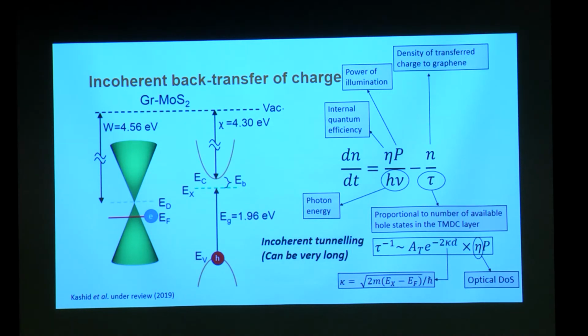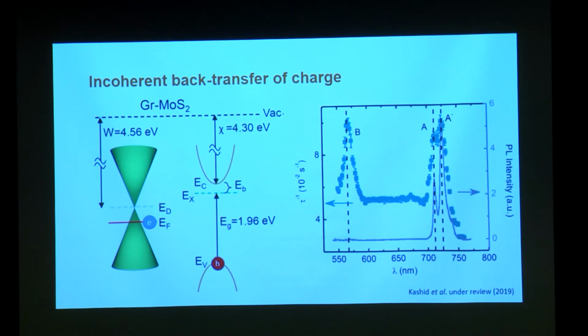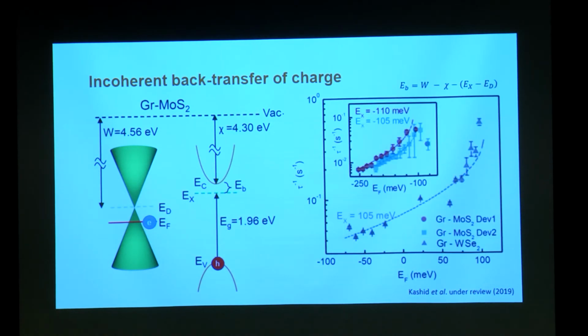experiments. So to prove this, first we looked at how the transfer rate depends on the optical density of states. You can see these are experimentally obtained data that the tau inverse is exactly following the photoluminescence of the chalcogen layer, showing that this rate is directly proportional to the optical density of states. That's number one. The second point is, does it depend exponentially on the energy difference between the Fermi energy and the excitonic state? Answer to that question is also correct.